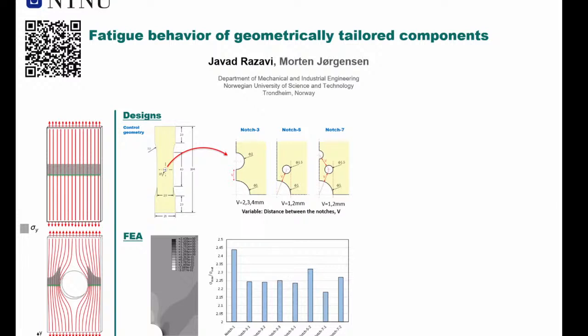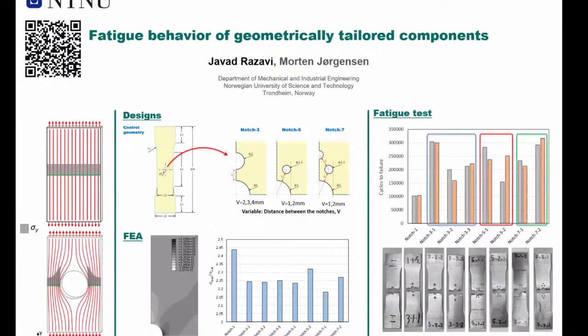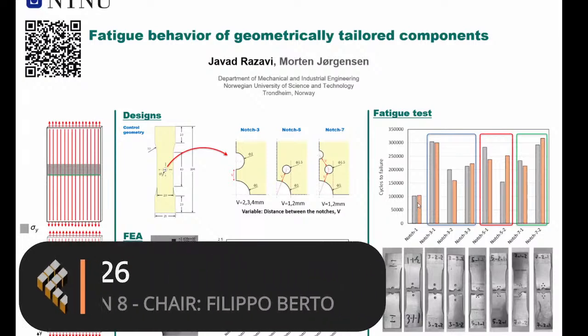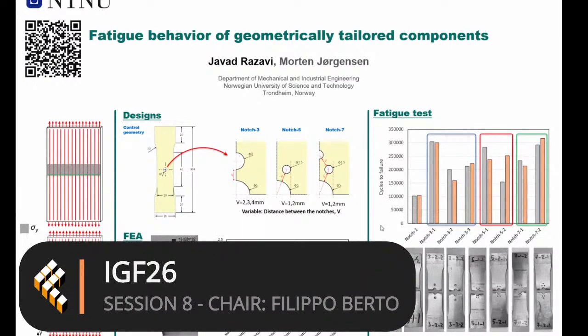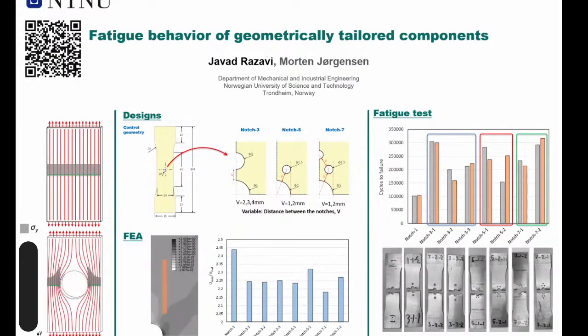So we performed some preliminary fatigue analysis on the samples that were fabricated using this geometry. The samples were made of aluminum alloy, and they were machined to the geometries that we had. So here you can see the results of the fatigue test in all cases, including the control specimen. The applied load was kept constant, 4.5 kilonewton as the maximum load, and the frequency was 20 hertz. You can see that in all cases, we had an increase of fatigue life from around 100,000 for the control specimen with only a circular notch to even up to 300,000 for at least one of the cases in each batch.